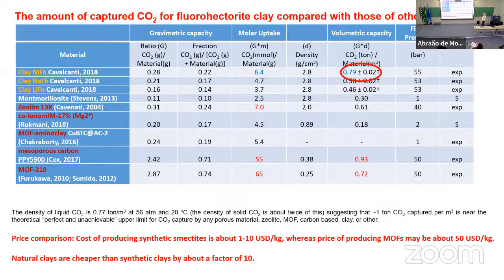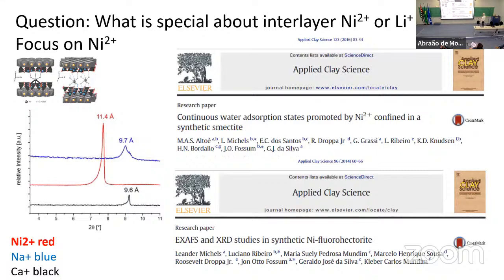We also, in this paper, did gravimetric experiments. So we found that for the case of nickel in our clay, we captured an amount of CO2 comparable to the best materials. So it means that the clay is a good performer in terms of, say, volumetric capacity for CO2 capture. So why is nickel such a good case?